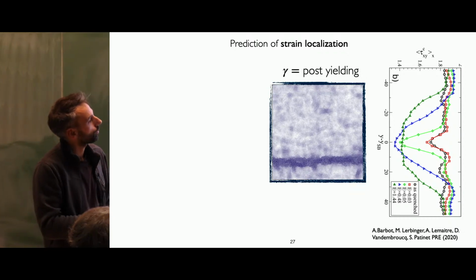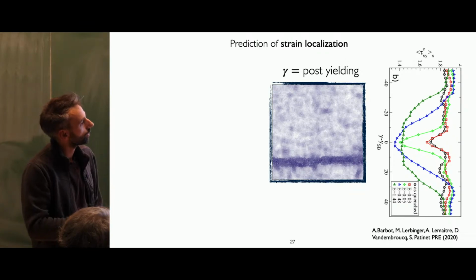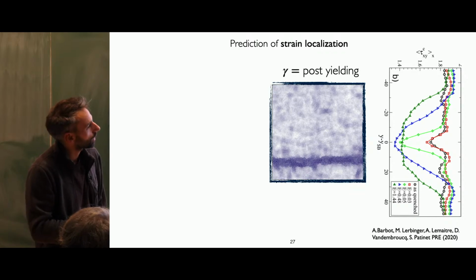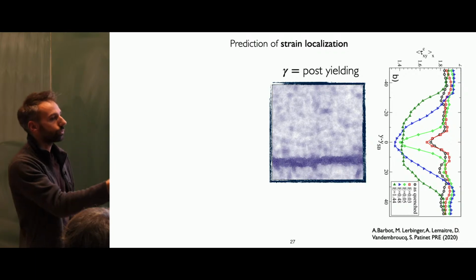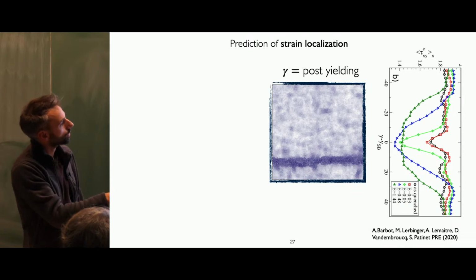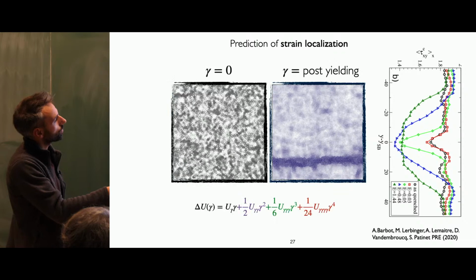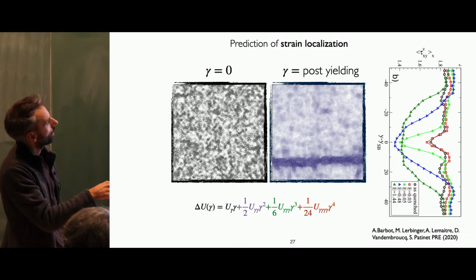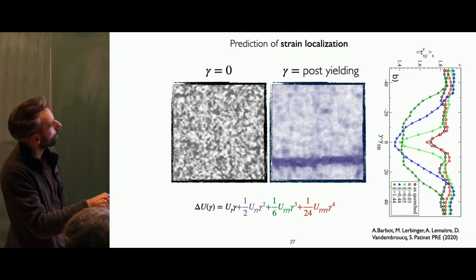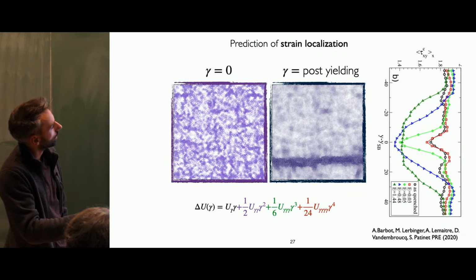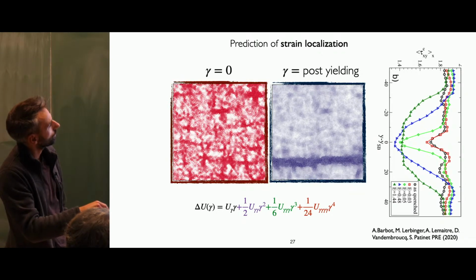And this is an ensemble average over many realizations, but they look at the local yield stress where they center the distribution of the system to the direction of the shear band. So 0 is where you will have the shear band. Of course, close to the shear band, you will have small local yield stress, but they saw that in the as-quenched state, there was some sign of polarization where in the system there will be a hint of where you will nucleate strain localization. But this was averaged over many samples. I wanted to see with my tools, can I do this at the level of one system? So here I'm showing you the strain energy expansion per particle at zero strain, and then I take several terms from linear to nonlinear terms. And indeed, you see that even if it's noisy, you can see some of the sites where you will be able to nucleate a shear band.